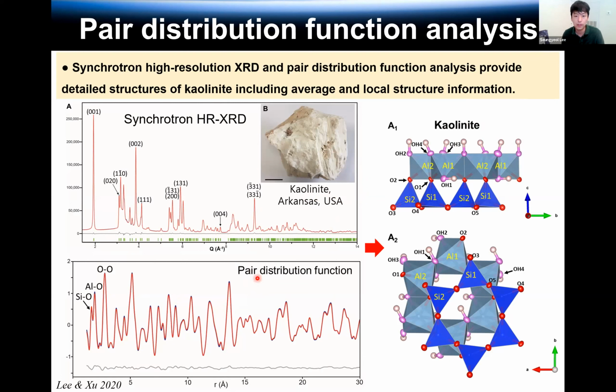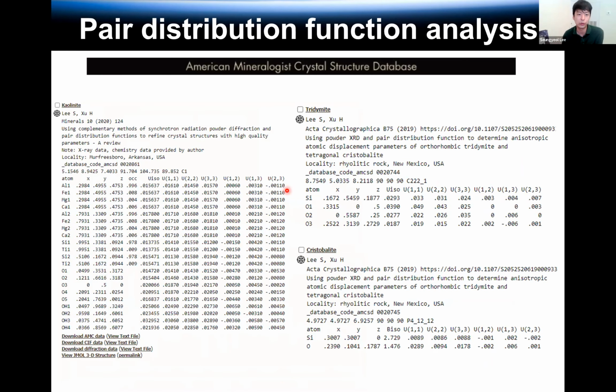Look at the PDF result. The first peak leads to the silicon oxygen distance, so now we can know the silicon oxygen distance from this pattern. The second peak leads to the aluminum oxygen distance, so we can know the aluminum oxygen distance. And the third peak is related to the oxygen-oxygen distance. This method is very powerful for studying the structure of minerals. Based on synchrotron high resolution diffraction combined with the pair distribution function method, I can provide the detailed crystal structure of kaolinite.